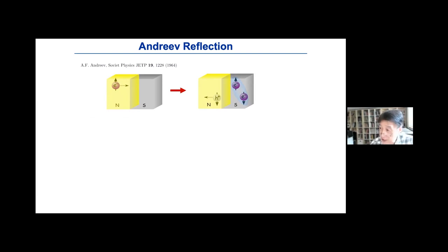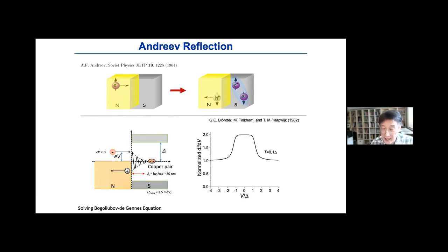These Andreev reflections usually appear as an enhancement of the interfacial conductance at zero magnetic field. Basically, just looking at how the conductance gets enhanced will tell us how perfect the interface is between the superconductor and the normal metal. And this enhancement can go up to 100% because all the electrons get reflected by the hole. Basically, I have 100% Andreev reflection, and then I expect to see the 100% enhancement.